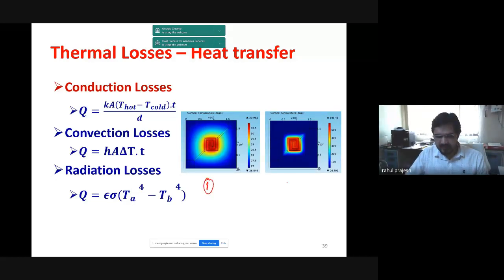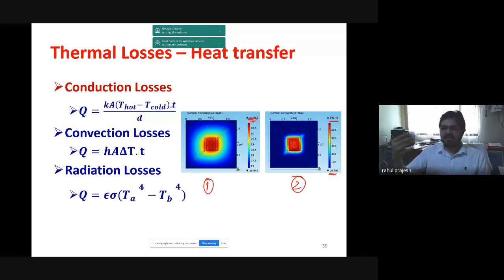You can see the difference. This is case 1 and case 2. In case 1, we have not removed the material from the back. In case 2, we have removed the material from the back. So you can see for a given power, there is hardly any change in temperature, 26 to 30 degrees centigrade only. But when you remove the material from the back, you see it is 26 degrees to 585 degrees centigrade. So that much increase in temperature you are able to get. This is the advantage of removing material from the back.